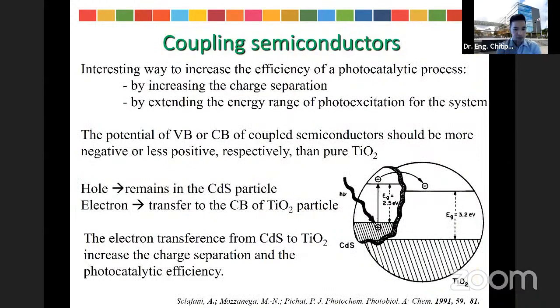And another way to improve the photocatalytic activity of the nanomaterial is the coupling with another semiconductor that I mentioned in the previous slide. For example, the coupling between the TiO2 and the cadmium sulfide, as I showed in this slide. The coupling of these two phases can generate the PN heterojunction of the p-type cadmium sulfide and the n-type TiO2, which are semiconductor photocatalysts. So the formation of the heterojunction can enhance the electron transfer from the cadmium sulfide to the TiO2, leading to improved charge separation and photocatalytic performance of this material.